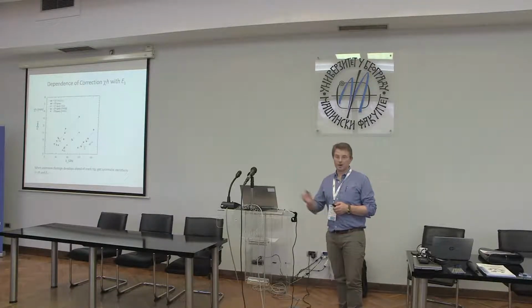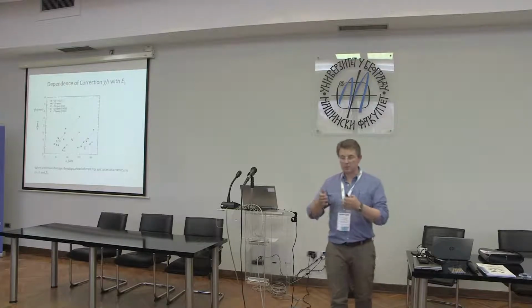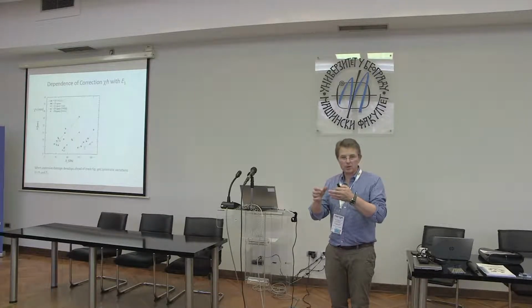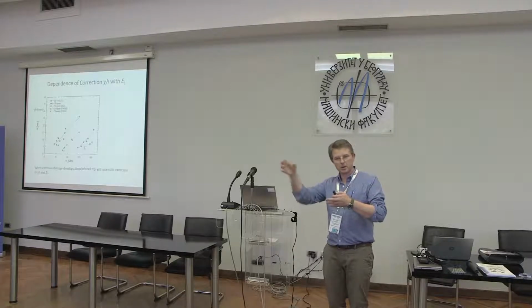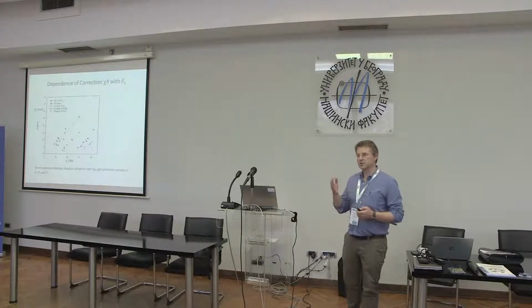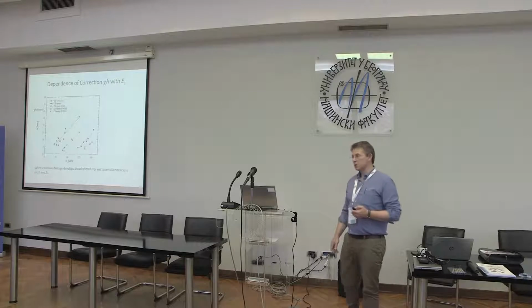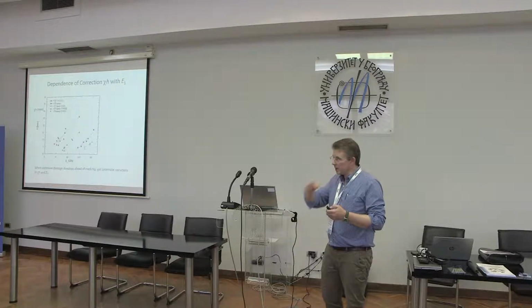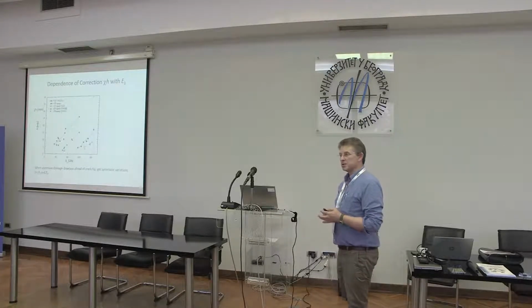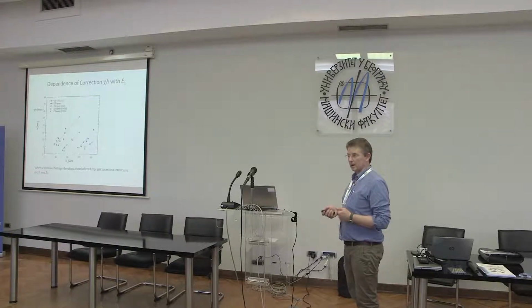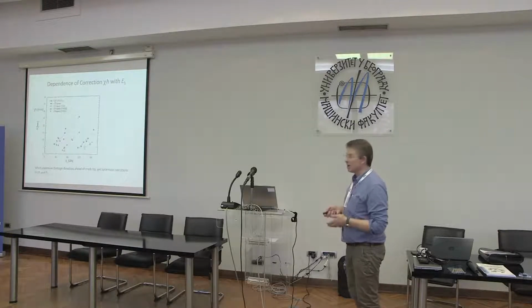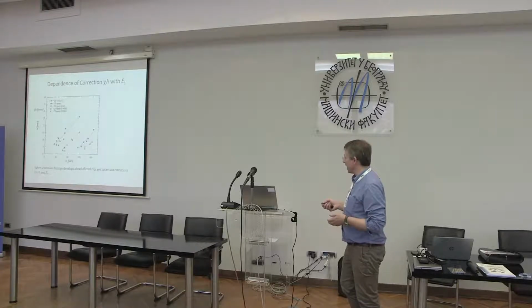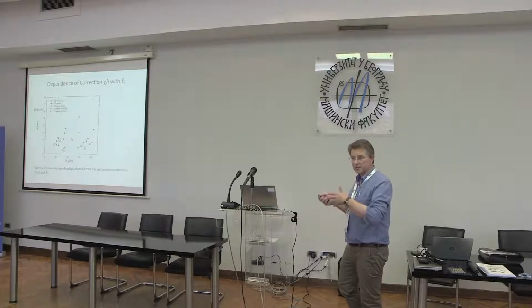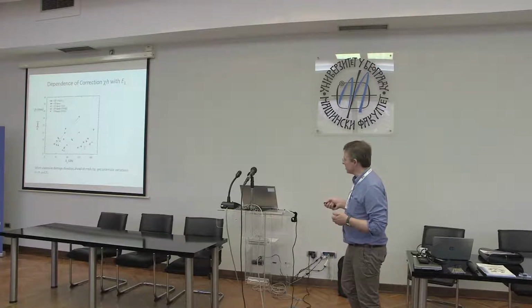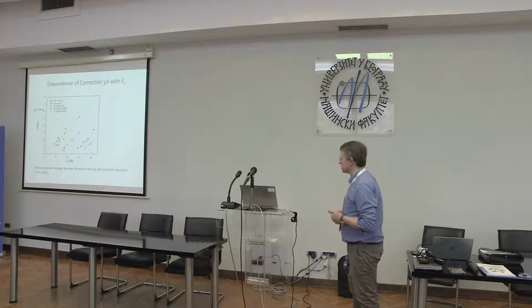So if someone in the lab is just measuring the extent of a crack, and you haven't noticed that ahead of the crack there's quite a lot of stuff going on, but it's discontinuous, it hasn't met up, what do you measure? Typically one will measure the continuous crack, and you would then systematically underestimate the crack length. That systematic crack length underestimation has knock-on effects on the analysis right the way through. So this really is just an indicator of what's happening across a range of specimens.